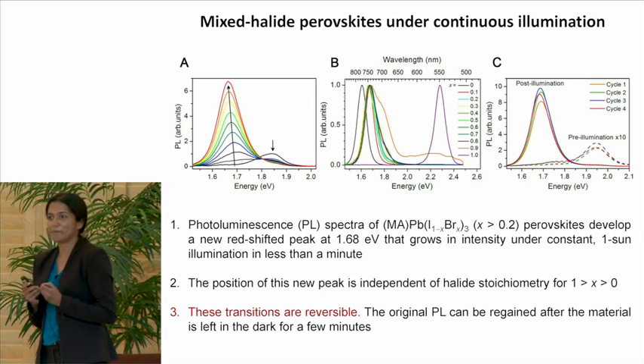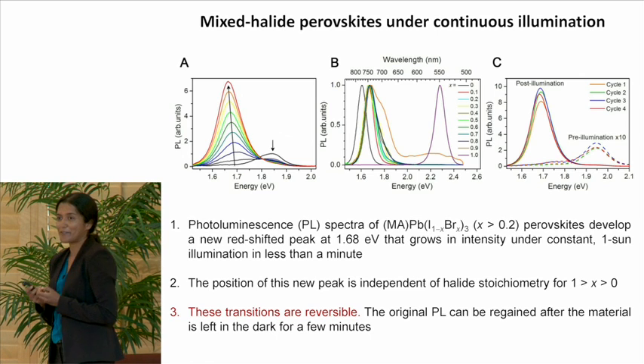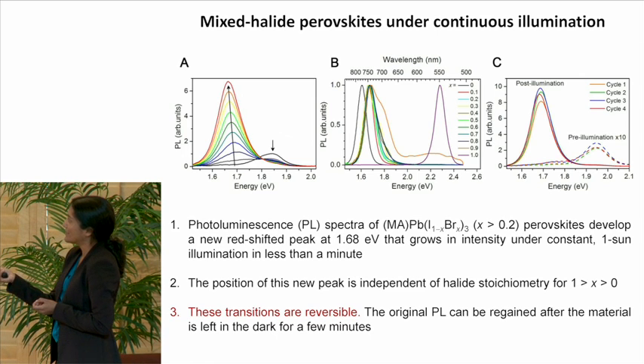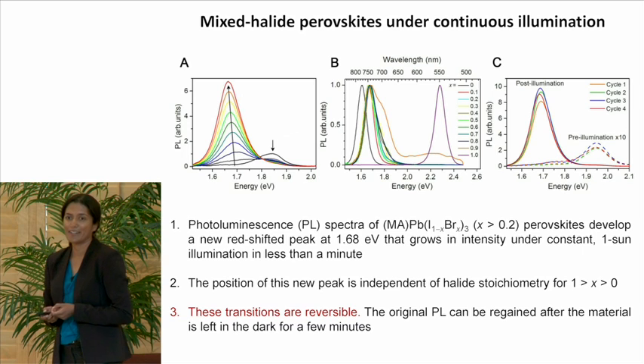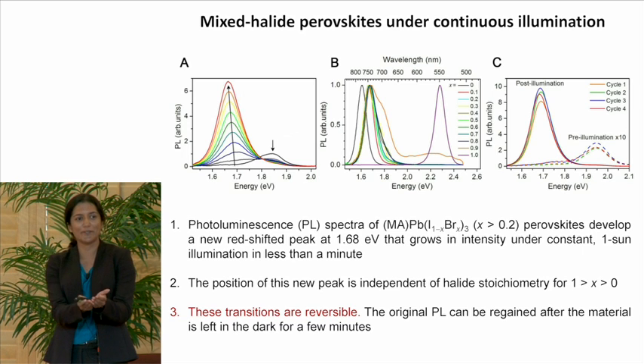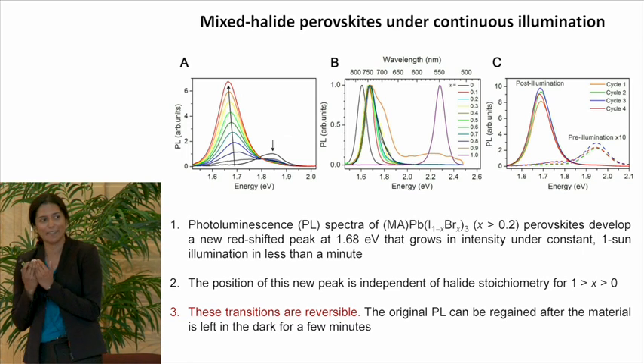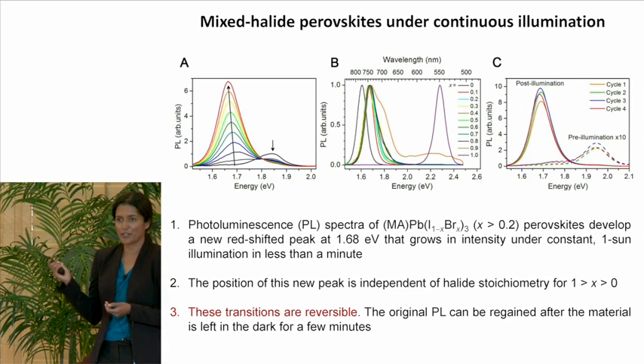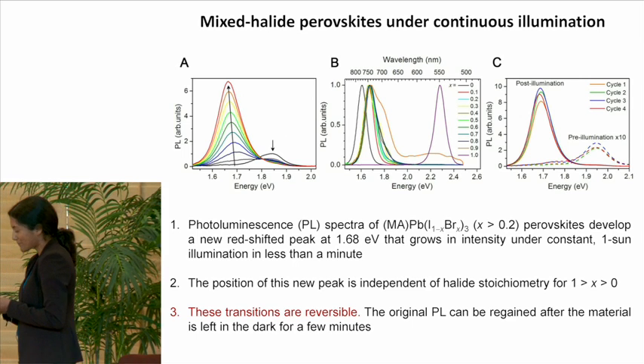And what's really surprising to me about this transformation is that it's reversible. When you turn off the light, you regenerate the initial material, and when you turn on the light, you get this new low-energy PL, and you can cycle between this. Eric has done this several times. Here I show you data for 4 of these cycles.